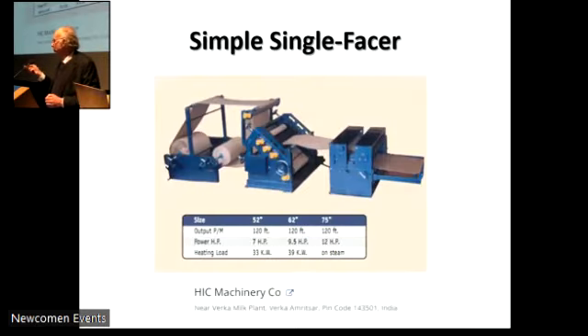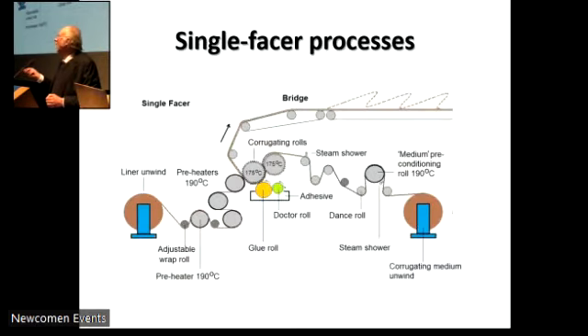These are heated, and they're actually quite hot. They're 175 degrees C as an average operating temperature. And the heat and the moisture which you've applied in a steam shower beforehand enable you to distort the sheet of board out of its plane to form our sinusoidal characteristic fluting. That is then carried around on the second fluting roll and brought up against the liner, which itself will have been preconditioned with heat and moisture.